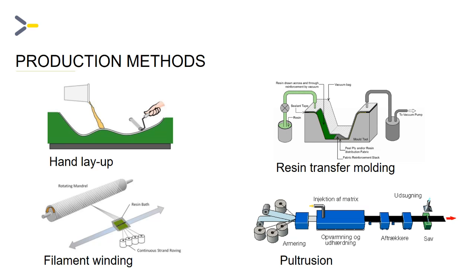After the stacking, normally you put your element in a bag and suck the air out. And on the other hand, you are opening a valve where you actually inject the resin in your whole mold. With this process, you can manufacture wind turbine wings, for instance, and huge boat hulls as well. And this manufacturing method is much more efficient, and you have much better fiber orientation compared with the hand layout process.